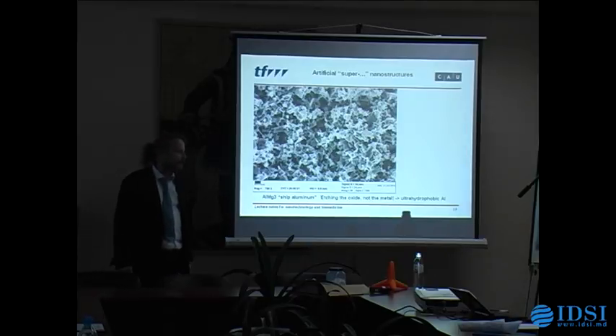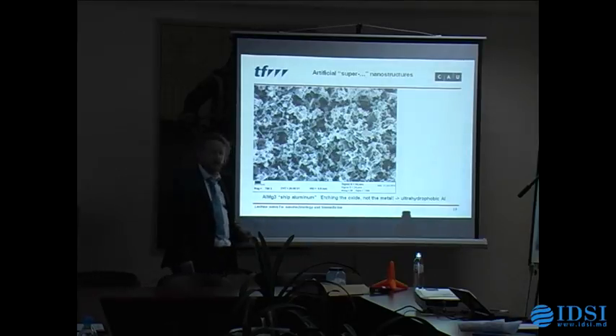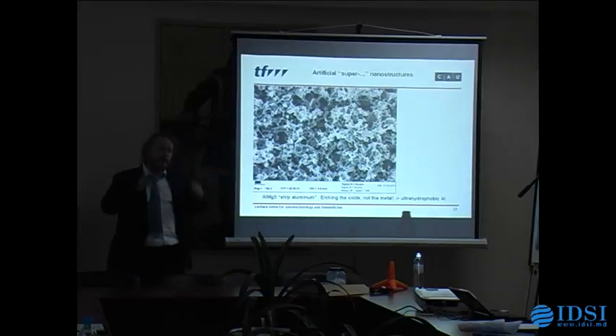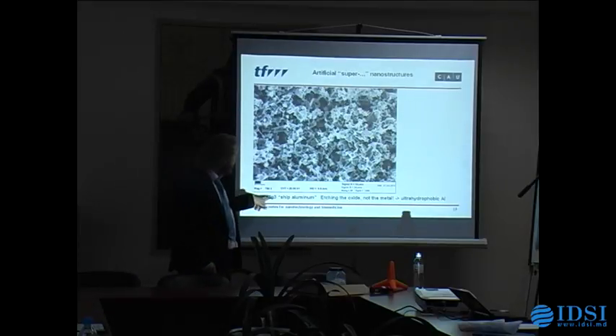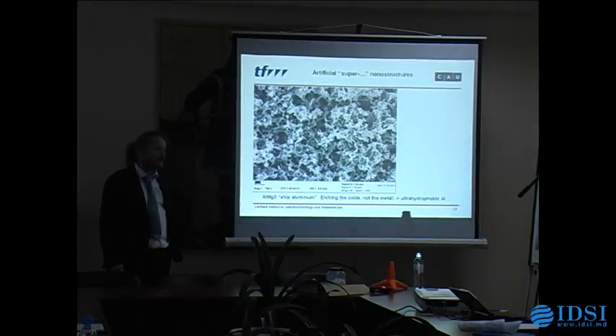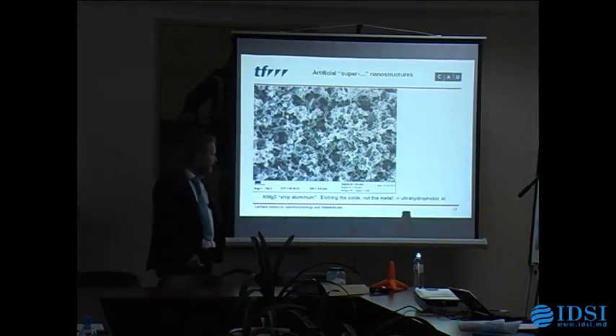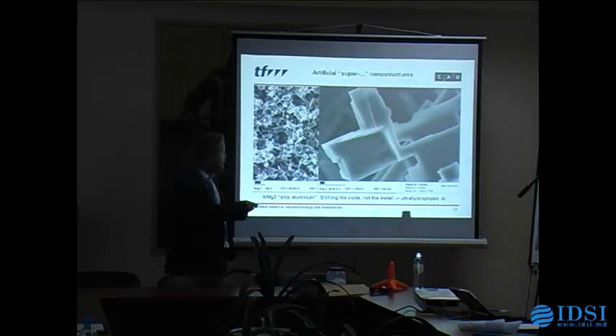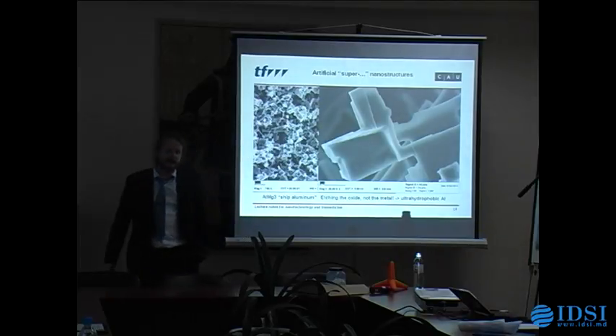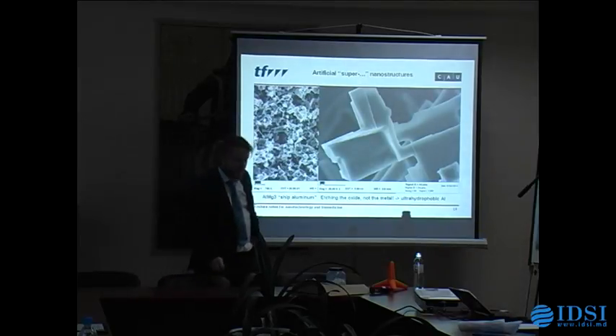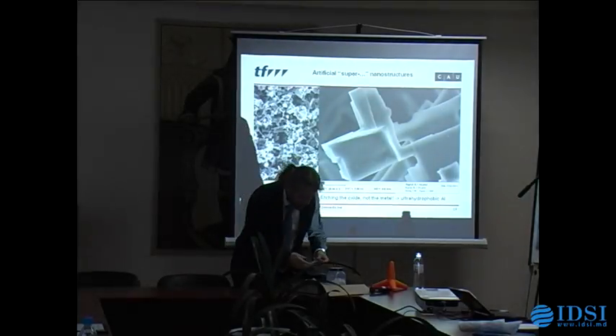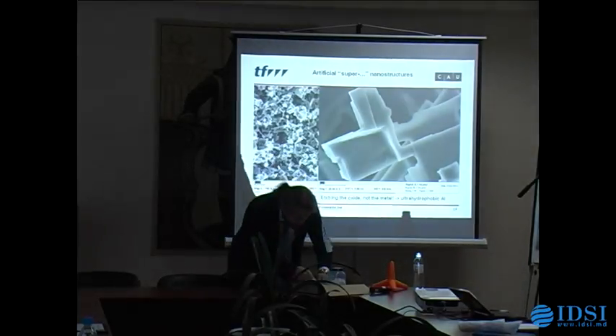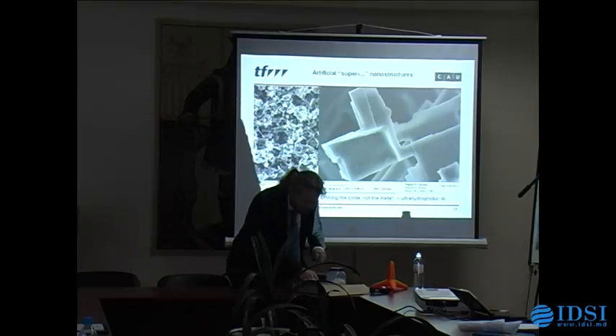So I'm coming from University of Kiel, which is close to the Baltic Sea, so ships are quite of interest there. And so we took some ship aluminum, AlMg3, which is an aluminum alloy, and these guys are etching it in such a manner, you can see it here in the magnification, that you have only those crystalline facets which are low energetic. And I have here some of those, some kept dry.